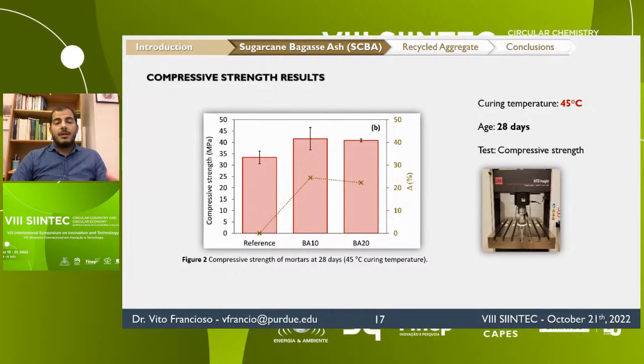Therefore, from here, I performed a secondary experimental campaign to estimate the variation of cement content required to obtain a compressive strength equal to the compressive strength of the reference mortar without sugarcane bagasse ash, depending on the ash replacement. The results of this additional experimental campaign contributed as an input for the life cycle assessment.